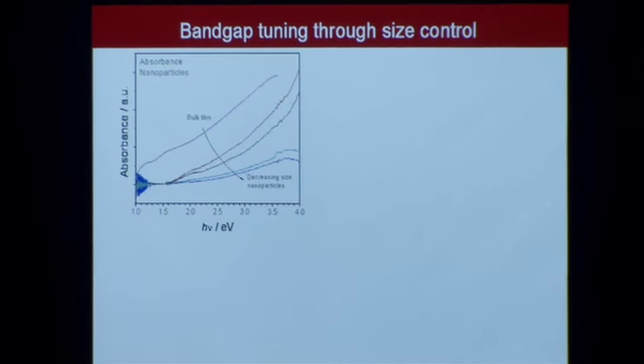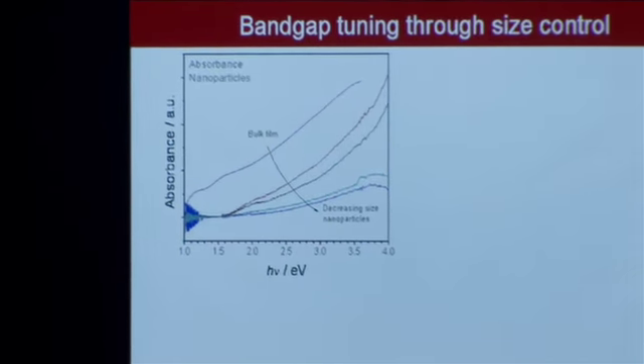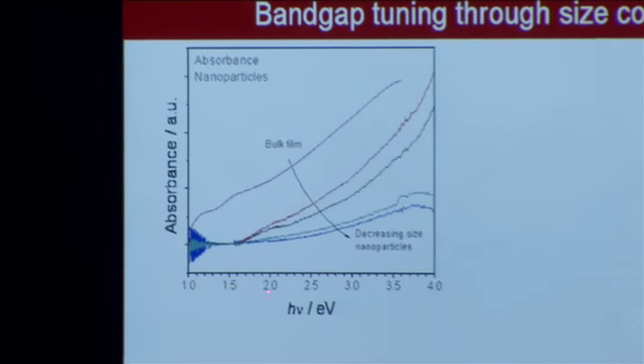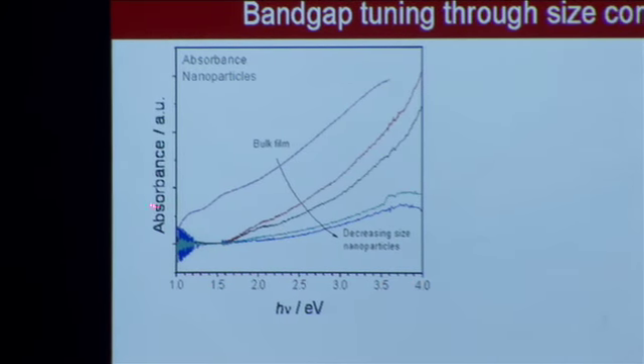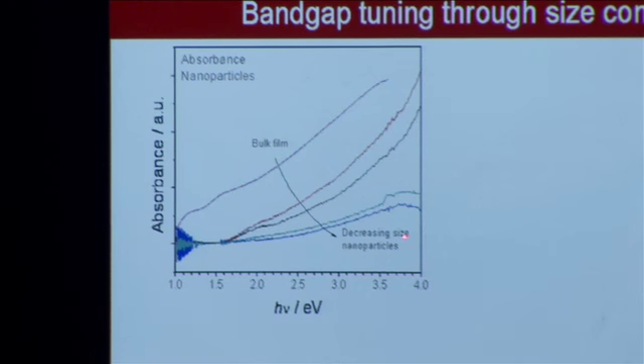We want to see, is there a blue shift in the band gap as we expect? So here's the absorbance spectrum as a function of the photon energy. This is a bulk film. These are the nanoparticles. And what I want to show you is that as a function of size, as we go to smaller and smaller size nanoparticles, you see two effects. First of all, you're getting less and less absorption of light, which is expected because the particles are smaller, there's less optical path length. But you also see that the onset for absorption is shifting to the right, which in this case means it's a blue shift in the onset of absorption.